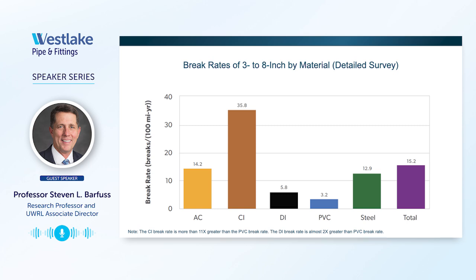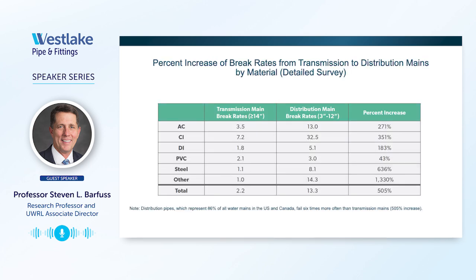I just point out that the difference between this PVC and this cast iron is 11 times, and it's almost 2 times just ductile iron to PVC. So there is quite some significant differences in terms of pipe material sustainability, or pipe material able to resist breaks.